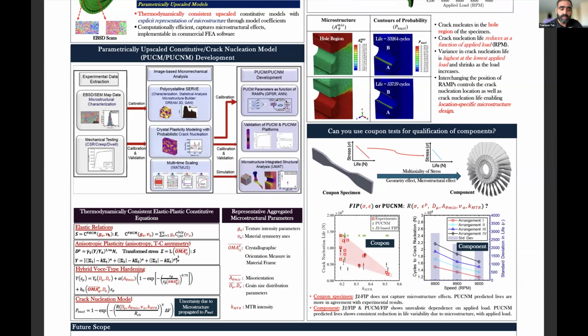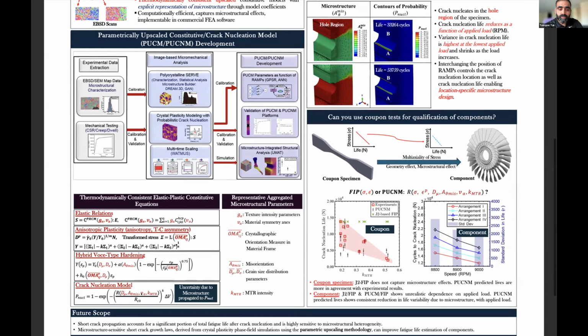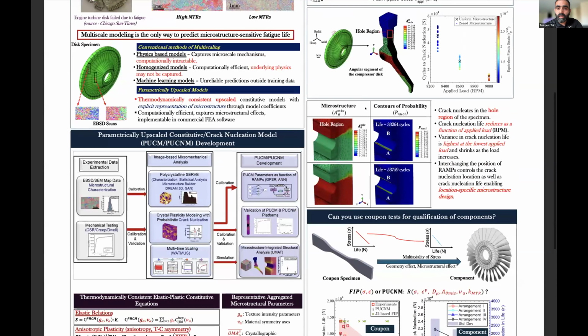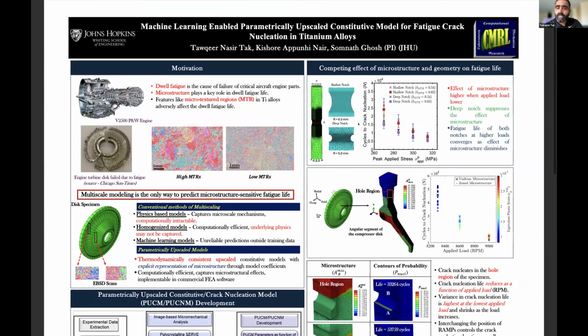As we can see, the material response is a function of the underlying microstructure. Here you can see the elasticity tensor is a function of the underlying crystallographic texture. Similarly, plastic response is a function of the grain size and misorientation. In addition to this, we have a crack nucleation probabilistic framework for crack nucleation prediction, which is again a function of the underlying microstructure.